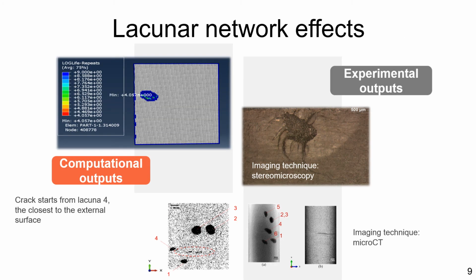The healthy lacunar network configuration serves as a preliminary validation for the implemented computational models. Three different categories of samples are selected: 3 specimens without lacuna, 3 with 1 lacuna, 3 with 6 lacunae, and 3 notch samples with 6 lacunae. The results for tensile tests show a decrease in elongation at break and a more brittle behavior for samples with a higher number of lacunae.